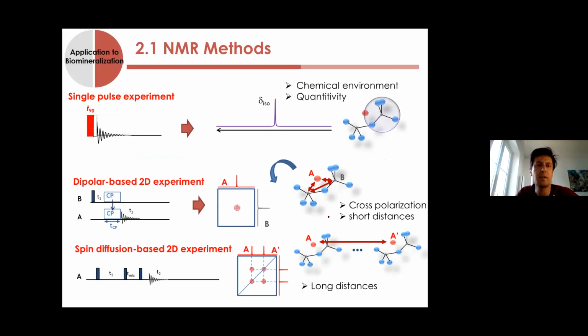The most basic experiment is called the single pulse experiment, where you make the excitation of one given spin, one given nucleus, and then look at the response, meaning the resonance. The position of the resonance in terms of frequency, meaning chemical shift, gives you information about the chemical environment. But it also gives you an interesting information, the quantitativity. NMR is quantitative, meaning you can make comparisons and get information about the ratio of two different environments.